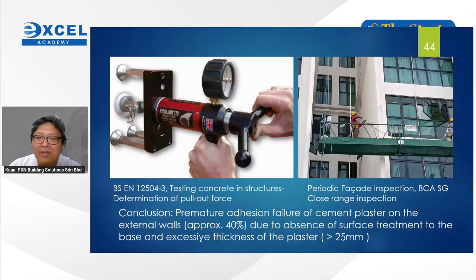I think in this case it is poor QA/QC. Okay, that may be the wrong application method as well. The absence of surface treatment and the excessive thickness are the causes of the delamination. So as you can see, these are the type of solid evidence that can tell the root cause so convincingly. Okay, but we have to do a number of tests.